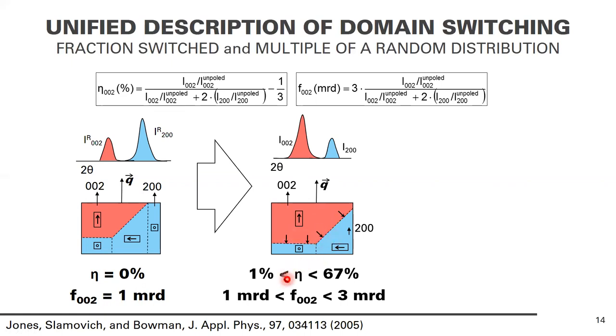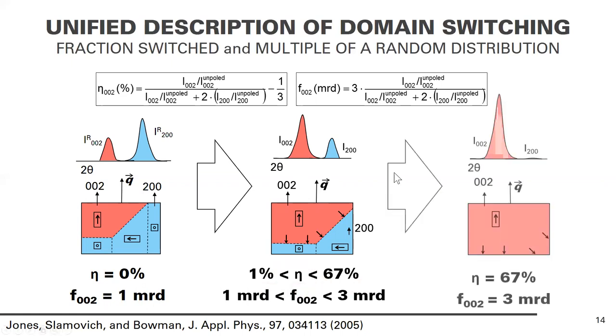And then our switching fraction increases to somewhere between 0 and 67%, and the multiple of a random somewhere between 1 and 3. And then in the fully polled, completely saturated case, you can see that the domain switching fraction is 67%. So what this means is that 67% of the material, this blue, has now turned to pink, okay? Or equivalently, the F002 is three multiples of a random distribution. So we have three times the amount of these orientations relative to what we saw in a randomly oriented sample.